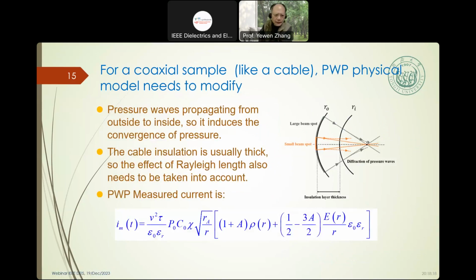Another aspect is for the coaxial sample, like a cable, where the PWP physical model needs to be modified. The propagation is not uniform. It is like a focus. The pressure propagation from the outside to inside induces convergence of the pressure. So here it is like this. The problem is the cable insulation is usually thick, some 10 millimeters, 20 millimeters, now someone is over 20 millimeters, so it is very thick for the measurement. So the effect is a focus like this, and the propagation is around, so it also needs to be taken into account.